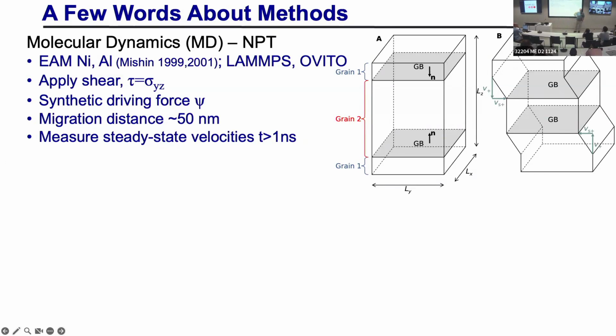If I lower the free energy of the crystal in the middle relative to the crystal on the outside, then these two grain boundaries should move outward, such that you increase the amount of the low energy orientation. So we do this by shifting the chemical potential of one grain relative to the other. We call this a synthetic driving force, and that drives grain boundary migration.